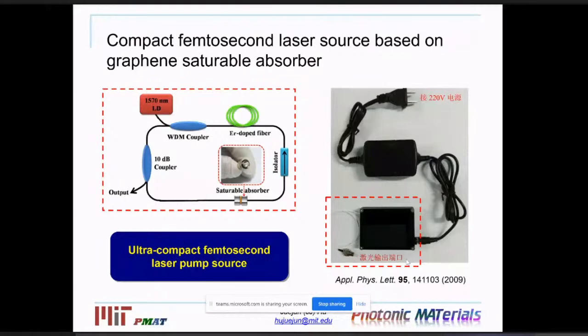That's why we have collaborated with Juejun Luo's group at Xiamen University in China. His group has pioneered an ultra-compact femtosecond laser pump source. It's essentially based on a saturable absorber made of graphene materials, so that when the light is amplified and passed through the saturable absorber, you can turn the light into very short pulses while maintaining a very small footprint. On the right-hand side is a photo of the laser they have demonstrated, and you can see the size here. This is only a few centimeters across, so it is compatible with integration in a compact sensor platform.